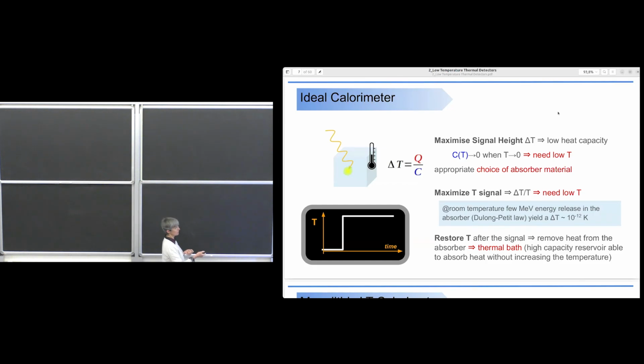And you may remember that heat capacity becomes negligible and virtually goes to zero when the temperature goes to zero. Because everything becomes frozen, you do not have any kind of degree of freedom, and therefore the heat capacity becomes negligible. So one solution is to go to low temperature, operate your detector at low temperature, and then choose a material that has a low heat capacity compared to others. And this will be discussed in a while. The second strategy is generally to maximize the signal.